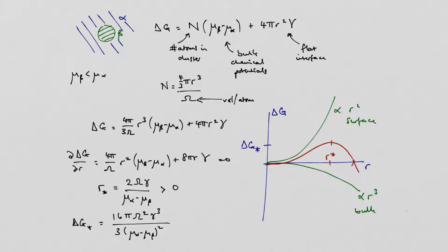Good. Okay. The energy barrier, if you remember, was about the chord between two points on the curve and whether the chord lay above the free energy curve or below the free energy curve, which depended upon the curvature, whether it's concave up or concave down. Yeah, it was about the energy of the two phases with slightly different compositions compared with the fully mixed, and whether the separation had energy higher or lower.